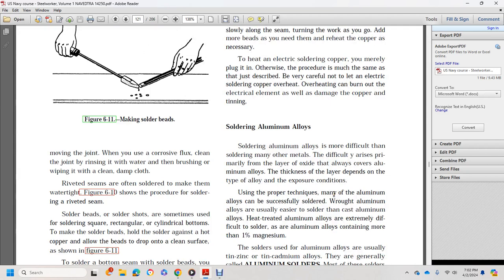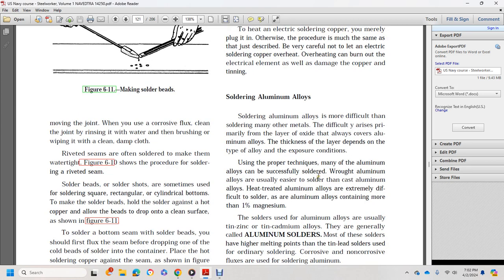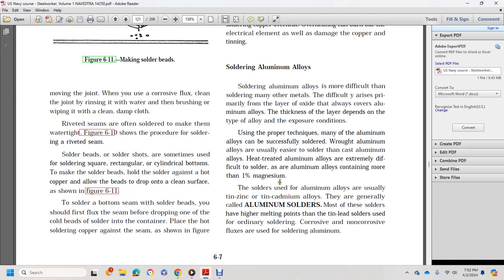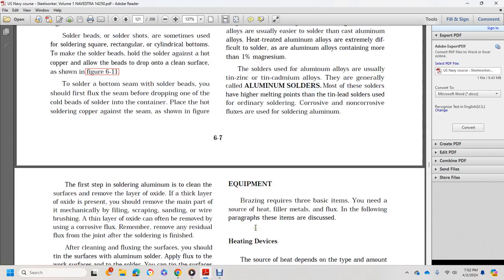Soldering aluminum alloys. Soldering aluminum alloys is more difficult than soldering many other metals. The difficulty arises primarily from the oxide layer. Aluminum always has an oxide layer on its surface, and the thickness of the layer depends on the type of alloy and exposure conditions. Use the proper techniques. Many aluminum alloys can be successfully soldered, Wrought aluminum alloys are usually easier to solder than cast aluminum alloys. Heat-treated aluminum is extremely difficult to solder, as are aluminum alloys containing more than 1% magnesium. Solders used on aluminum alloys, usually tin-zinc and tin-cadmium alloys, generally called aluminum solders, must have higher melting points than tin-lead solders. Even as in ordinary soldering, corrosive and non-corrosive fluxes are used in soldering aluminum.